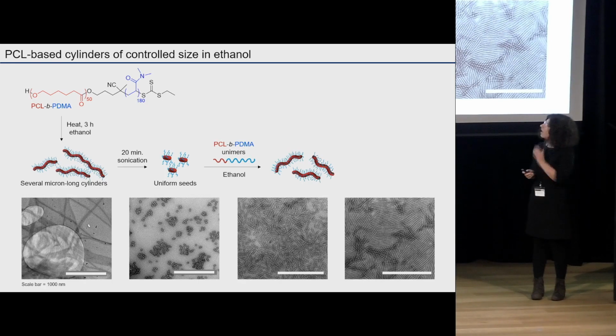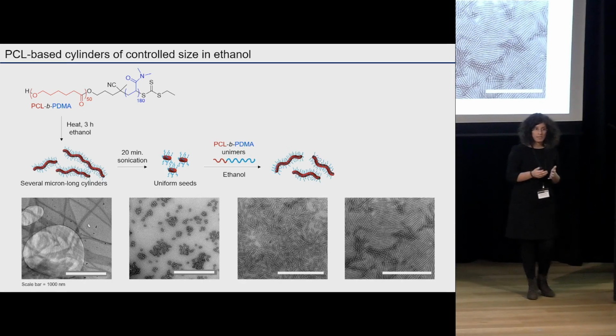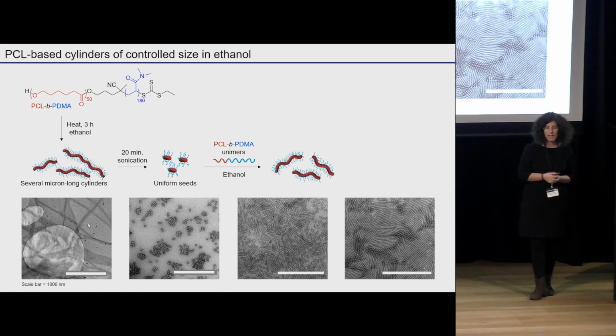where we use this polycaprolactone-based polymer. So polycaprolactone is a biocompatible and biodegradable polymer, and it's actually used in many devices approved by the FDA, for example. So it's approved for internal use. The other part of the polymer in blue is a polydimethylacrylamide, and that is a hydrophilic polymer. So this is an amphiphilic structure, so it has a hydrophobic component and a hydrophilic component, and it can self-assemble.